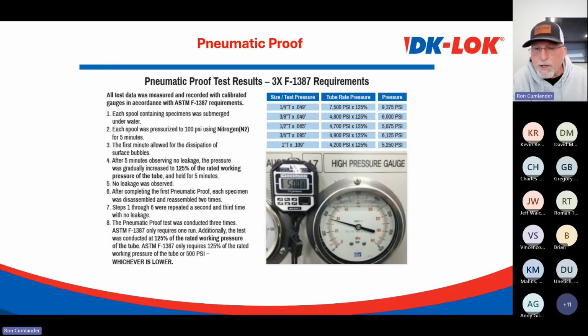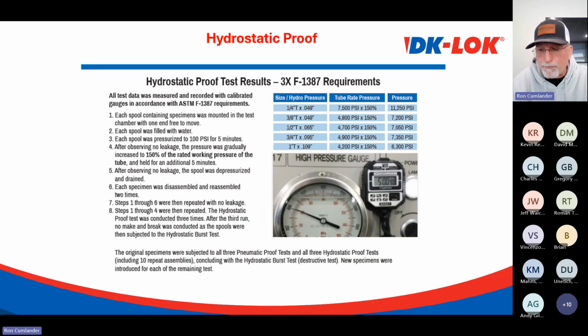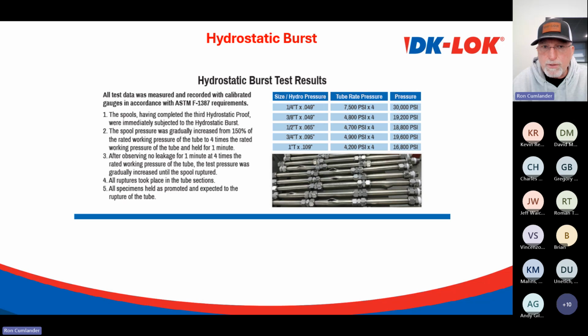And when we completed this with no leakage, we decided to go further. We shut down, depressurized. We did 2 make-and-breaks on every specimen, and we did a second run. No leakage. We shut down, 2 more make-and-breaks, did a third run. So we actually tripled the requirements of this particular test in comparison to the requirements of F-1387. Then we rolled right over into the hydrostatic proof test. We did the same thing here. We used the exact same specimens from the pneumatic proof, but we tripled the requirements here before we rolled over into the hydrostatic burst. And then, of course, we took the tubes to burst.